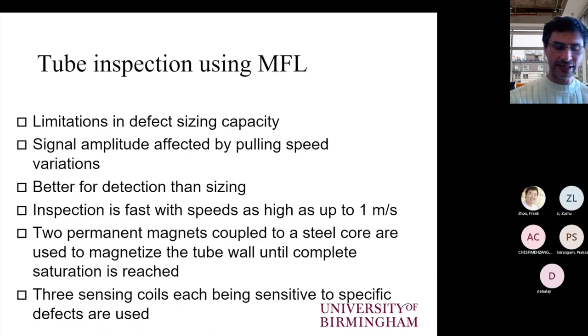Theoretically, we can also detect cracks, but MFL has restrictions in crack sensitivity, and the orientation of the crack and its location will affect its detectability. So typically, the orientation of the crack with respect to the flux lines has to be transverse, because if it's running longitudinal, then the flux leaking will be too low and will probably go undetected. So two cracks of the same size, depending on their orientation, can be the difference in detecting them or not detecting them.